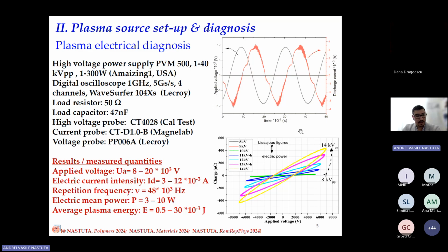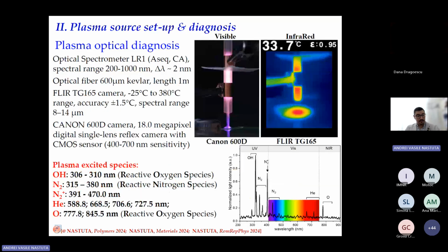If we are having this electrical condition, then we can say that we can ignite such a plasma. And here in this slide, we have a picture of the plasma. The dielectric quartz tube, some metallic copper electrodes. In between these two electrodes, we ignite this kilovolts voltage, and we have this plasma effluent that will go out of this tube. This is the active zone that we can use in the experiments.